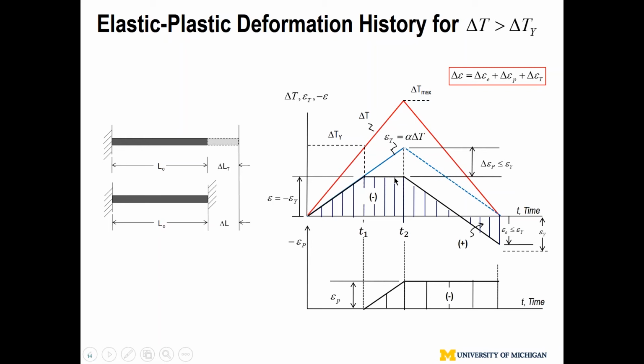So again, roughly this is consistent with the material handbook, say 30 KSI mild steel, and then the thermal expansion coefficient, and 30 million PSI Young's modulus. So what this says is I ended up with 154 degrees, even well below our cooking temperature, water boiling temperature. So what that says is if I exceed this temperature, I'm going to have a permanent effect. That means I'm going to have a reduced stress. Actually, this temperature is pretty benign, very easy to exceed.